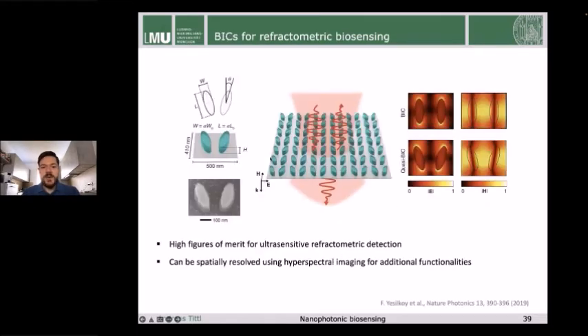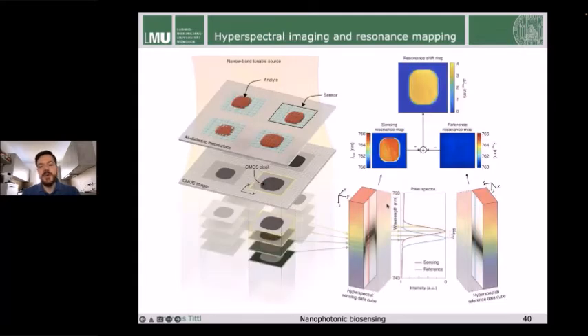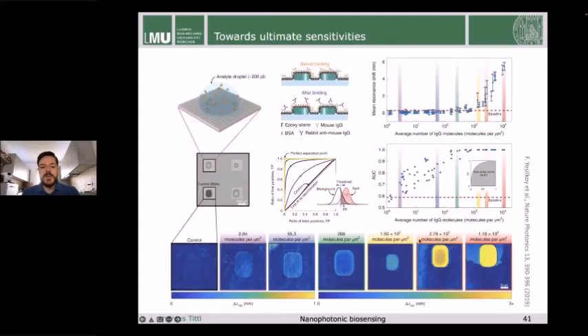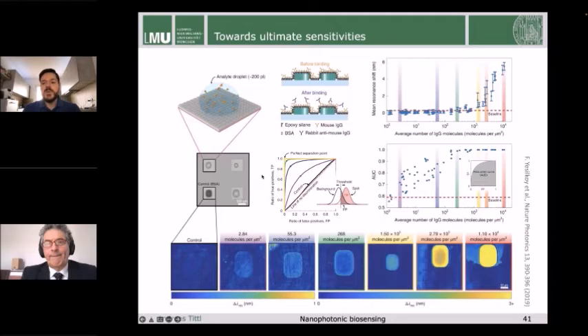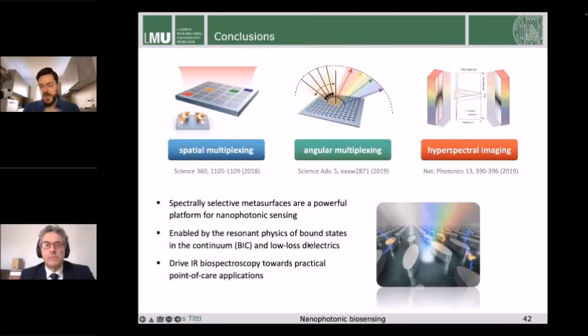And then finally, we also applied the same metasurface technology at visible wavelengths to use what is called refractometric sensing. Here we were able to go really to ultra low concentrations of analyte molecules, as low as 2.8 molecules per square micron, which is a tiny, tiny concentration, and really shows you how powerful these high Q, spectrally selective metasurfaces can be for sensing. And with that, I want to already come to my conclusion.